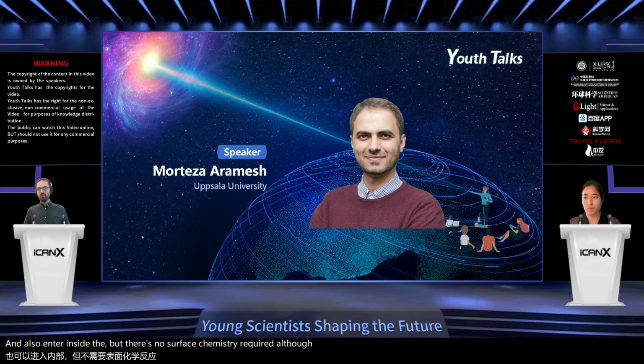Although one of the hypotheses that we have, and now we are testing it, is that by changing the surface chemistry, the kinetics of formation of this protrusion changes, and by changing this kinetics, it's possible to change the activation state of the cells as well.